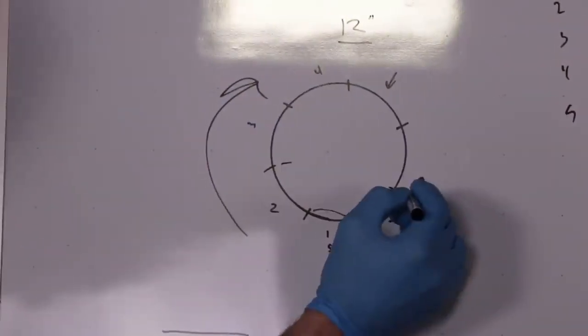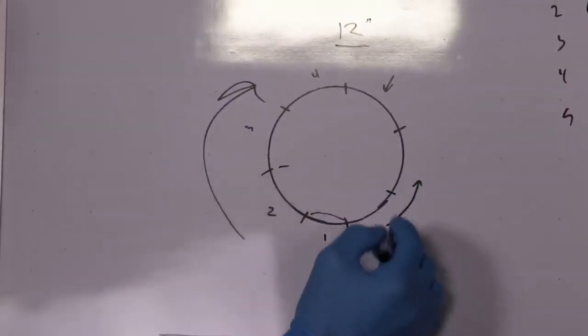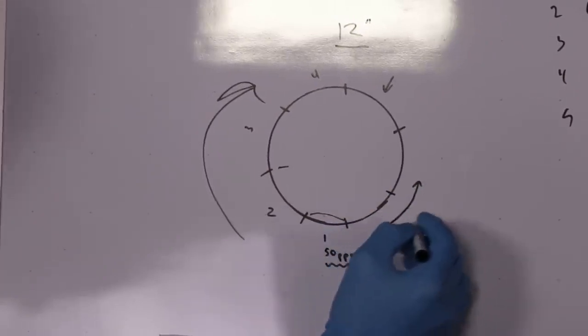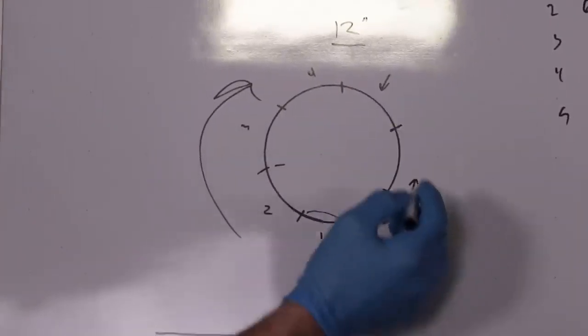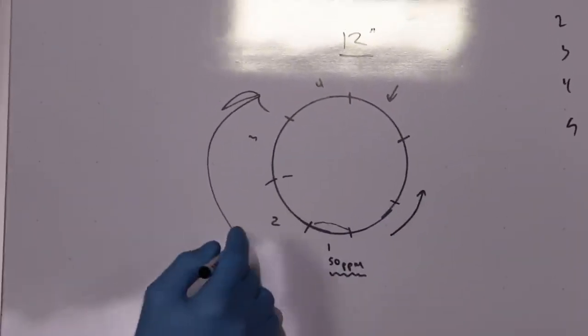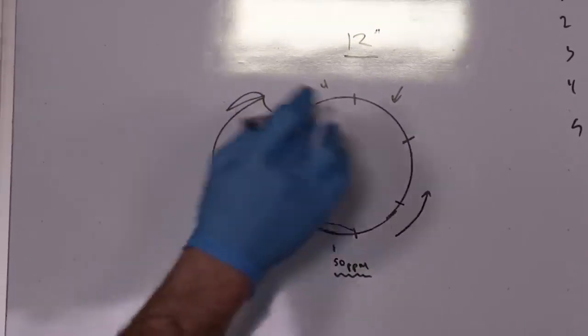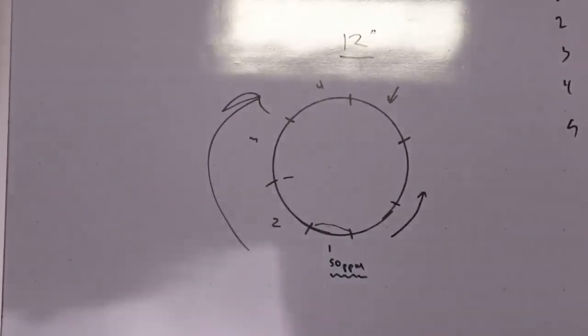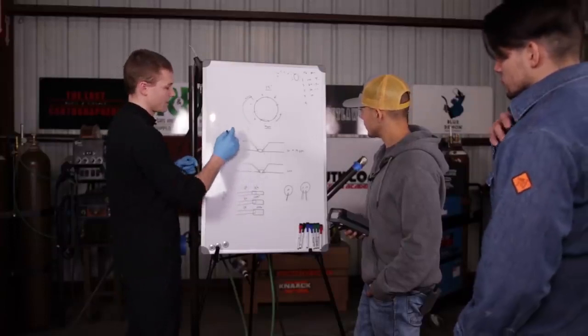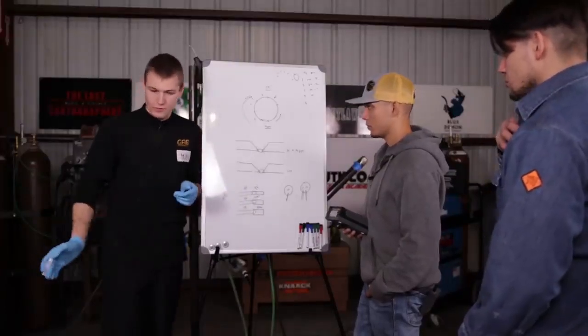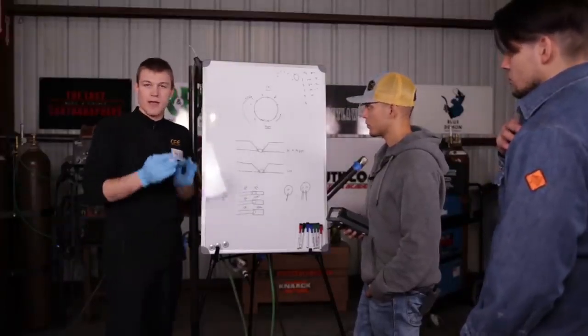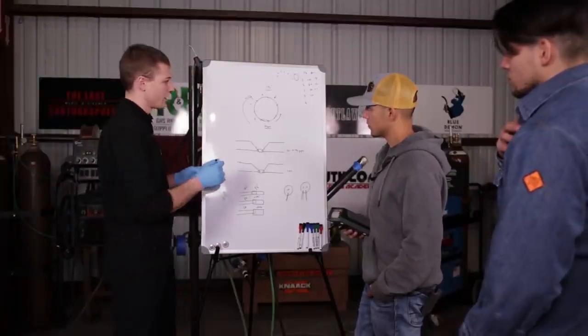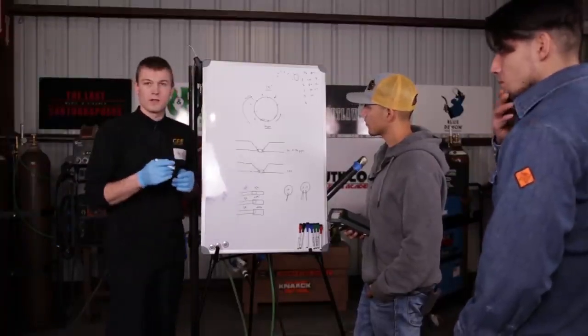So when you start going on the opposing side of the pipe, you're over half. Any deposited metal on this side is actually going to end up getting more silver and less parts per million of oxygen, so it's going to be even a better purge than the side you just welded on. A lot of the times you could take the bottle, flip it on the ground and roll it, and that will mix up any of the gases in the bottle and any impurities that may be lighter than argon that may come out first before the argon does. So that mixes up any impurities, which is also another trick to get a very high quality purge.